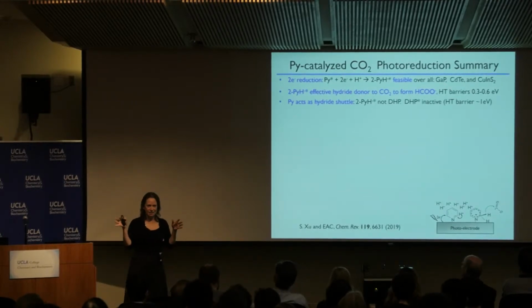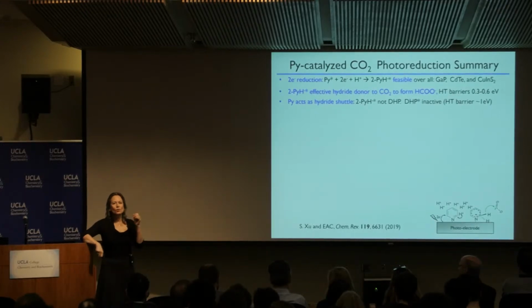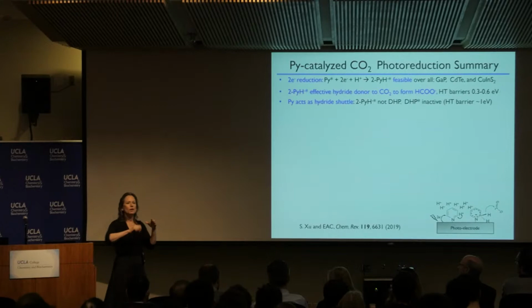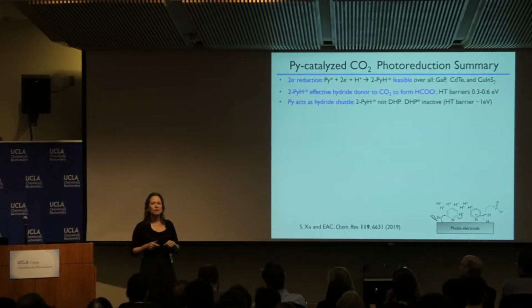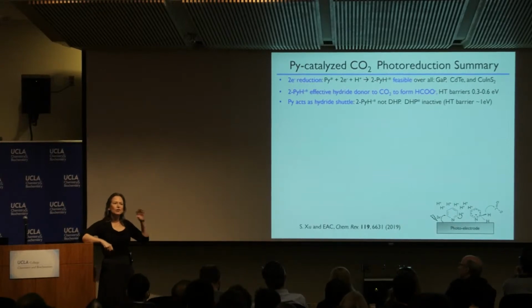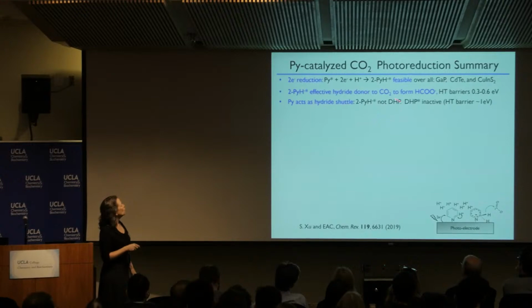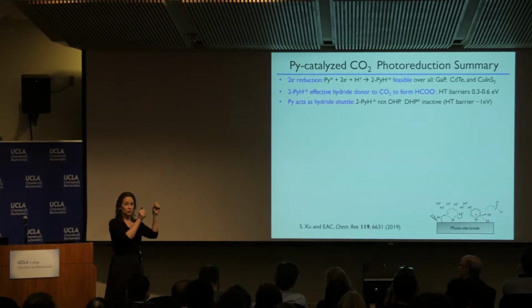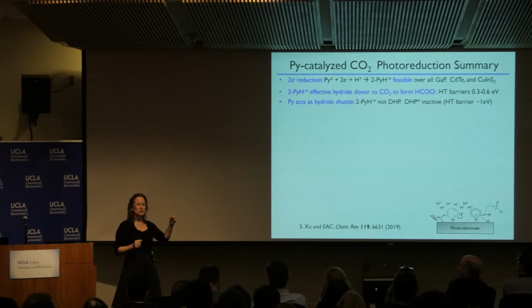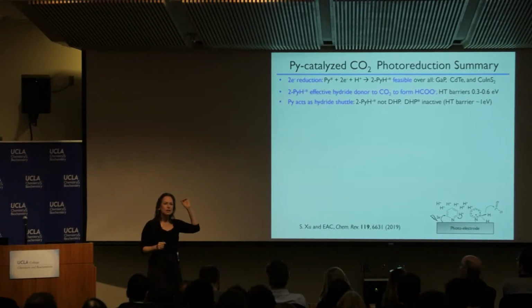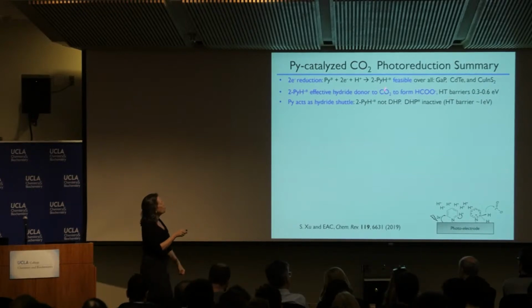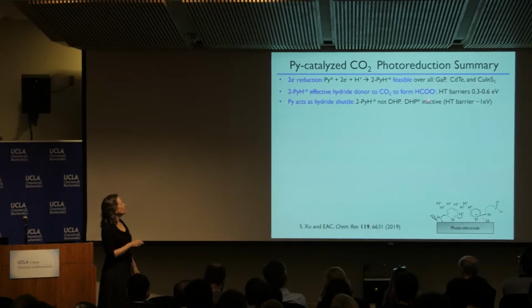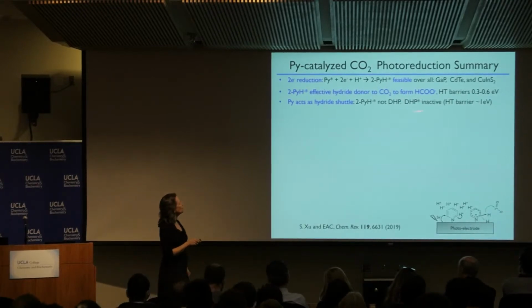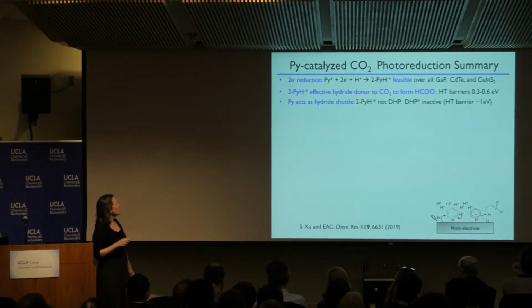And so the role of pyridine is that you need the pyridine in order to create this transient state for the hydride. If you have hydrogen on the surface, it's very different than on a metal surface where you have a hydride that then can do chemistry from the metal. It's so strongly bound to the semiconductor that that doesn't happen in the case of gallium phosphide. And so in this case, what the pyridine is doing is essentially providing a place for the hydride to form, okay, that it can't be transferred from the surface. It has to be that you get 2 photoexcited electrons plus a proton from solution to form this 2-pyridinide. And it's clear that dihydropyridine and adsorbed dihydropyridine, well, that's what the asterisk means, that it's adsorbed, they're both inactive, have too high barriers to do the chemistry.